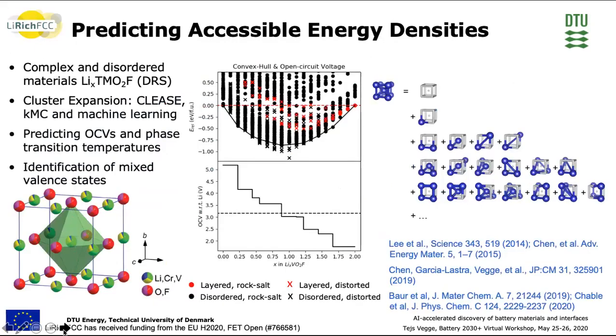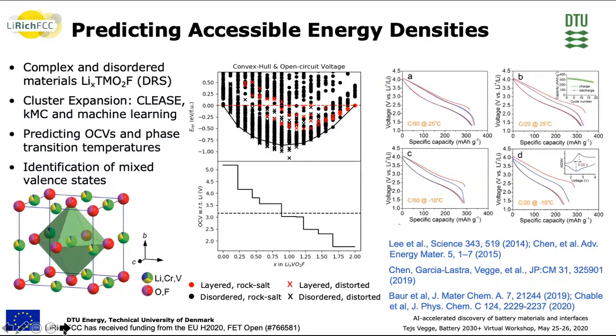So one example here is from a recent FET open project called Lithium-Rich FCC, where we're developing methods, this is Jinjun Chang and colleagues at DTU, that have combined cluster expansion methods with kinetic Monte Carlo and machine learning to be able to predict the accessible energy density in disordered rock salt materials, which are very complex to describe. And the reason for this is we really need to use atomic scale information to get the accuracy that is needed to predict the performance of materials. So if we want to predict, for instance, the OCV as a function of lithiation to compare directly to experiments, if we want to predict phase transition temperatures, we really need that very high accuracy.